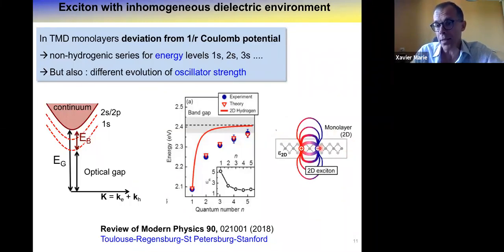When you deal with the ground state, the average distance, the Bohr radius basically, between the electron and hole is of the order of 1 nanometer. So basically the screening between the electron and the hole will be driven by the dielectric constant of your monolayer. But then when you go to the excited states, n equal 2, n equal 3, etc., the average distance between the electron and hole is larger, which means that you will be much more sensitive to the environment. So overall, the effective dielectric constant you have to consider will be smaller, especially if you are in vacuum or in air. So basically you can fit the dependence of the different excited exciton state energies by considering a different dielectric constant. And the key point is to consider this inhomogeneous dielectric environment.